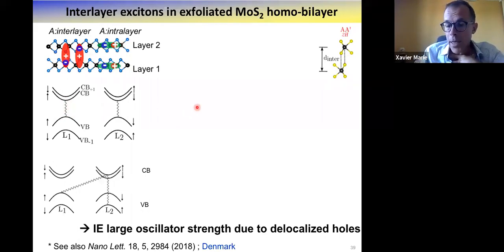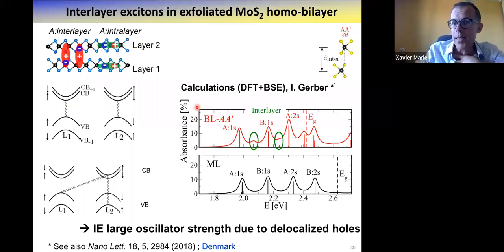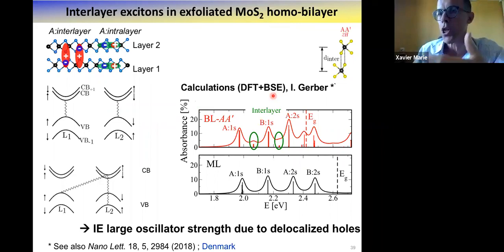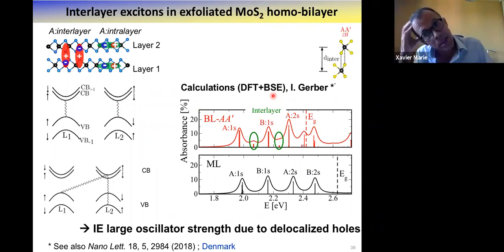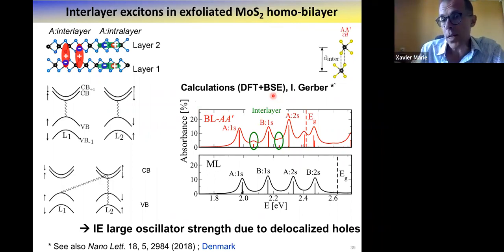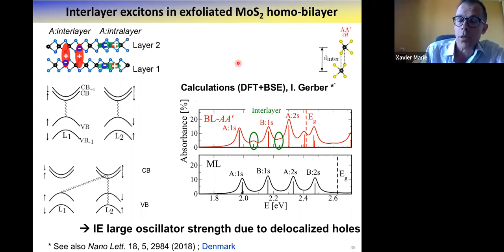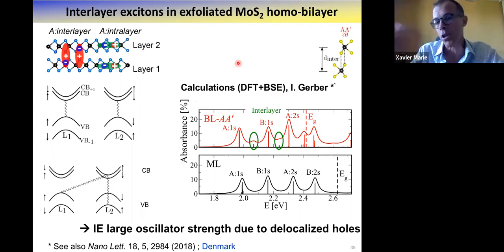But when you do a calculation, basically it's density functional theory to calculate the band structure at the GW level, for those who are familiar, and then the Bethe-Salpeter equation, which allows you to calculate the exciton spectra. From this, you can deduce the imaginary part of the dielectric constant, from which you get more or less the absorption. And you see here this calculation performed for the monolayer, so no surprise, one A exciton, B exciton.